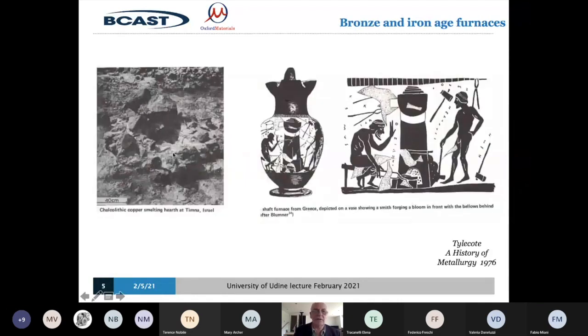You can see it's just really like a fire, like a campfire almost. But this was used to smelt copper, putting copper ore into that. As the fires got better and we put chimneys on the fire, as shown in this very nice picture painted on a pot from Greece, this is how they began to get better quality fires, and this is what led to hotter temperatures and allowed iron and wrought iron to be made.